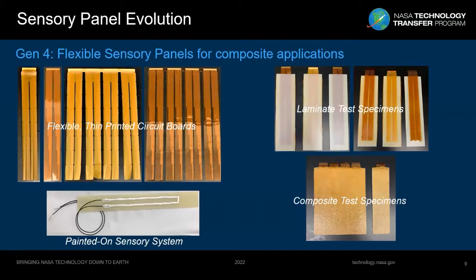On the right, you'll see the laminate test specimen. And so this is using a G10 plate to simulate a fiberglass sheet, and we have a front and a back face. And when they're laminate, essentially there's only one face sheet used. And so we're simulating if you were to take an existing structure, and these would be adhered to an existing structure. Below that is actually one that's fully encapsulated, so it's composite. So there is a front and a back face sheet, and the 2-finger sensory and the 4 or 8-fingered sensory printed traces are actually embedded inside the composite. And then the last thing shown here is a painted on version.